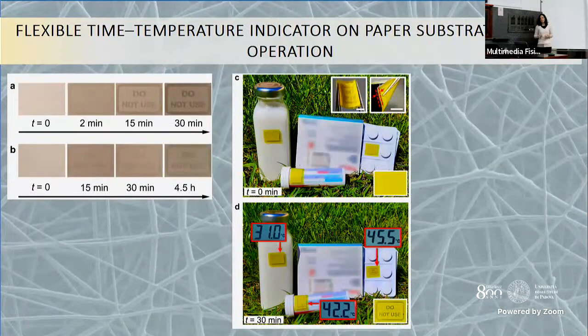And just to make an example of a device, we deposited these fibers on a commercial paper, and we covered these fibers with a yellow plastic foil, which acts as a UV filter, and we put the device on top of different goods that we exposed to sunlight, for example milk or some drugs. And of course, after 30 minutes of exposure, we measured the temperature of the goods. For milk, it was 31 Celsius, for this drug, 42. And as you can see, at the beginning you could not see anything on top of the label. But when the temperature increases, you can read the encoded message, that in this case was 'do not use'.